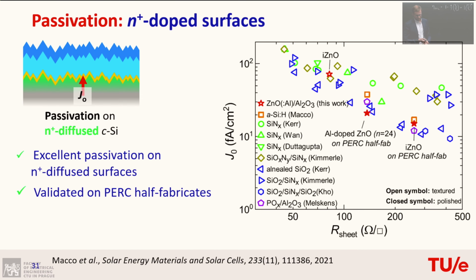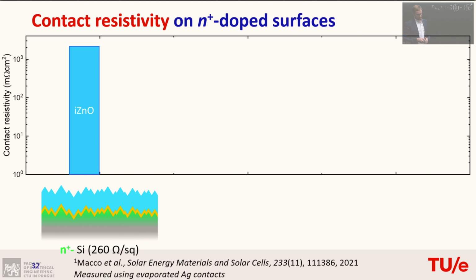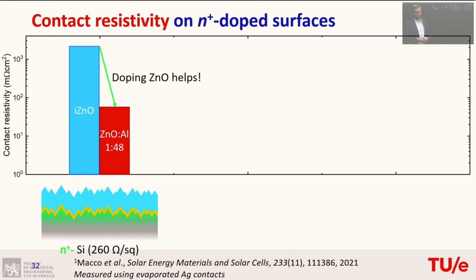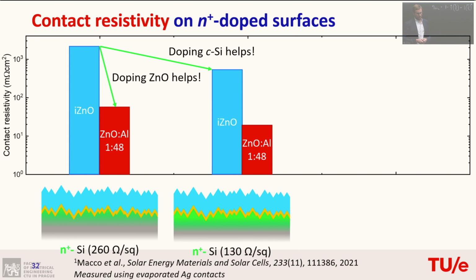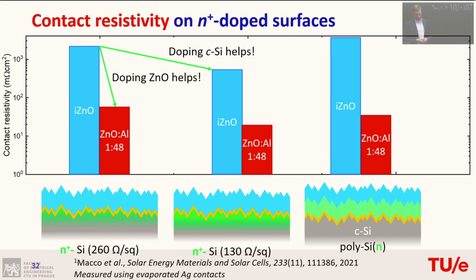So here again, the same picture. How good is then the passivation provided by our zinc oxide? We compare to other conventional materials that I discussed earlier, together with the phosphorus oxide. And now we see also here, for different kinds of doped surfaces, that we are over here and over here. So we are really in the same state-of-the-art regime, and you can use this basically on conventional N+ doped surfaces appearing in crystalline silicon cells nowadays. Then the contact resistivity, this also improves. So doping improves the contact resistivity. I typically want to have as low as possible contact resistivity to mitigate losses in cells. So here also on a different doping level, you see that the improvement is there, more heavily doped, and also on the N-type polysilicon case, the same argument holds.